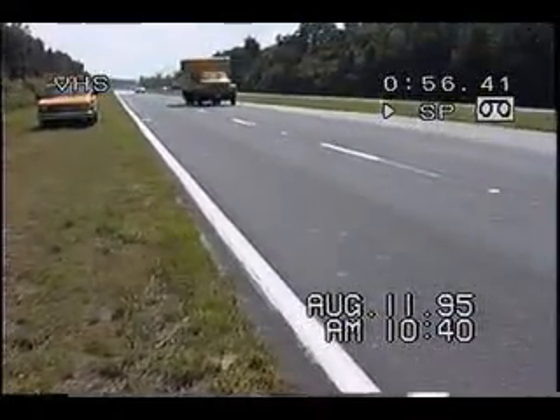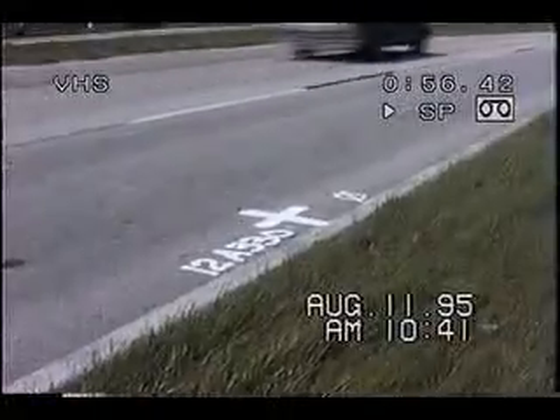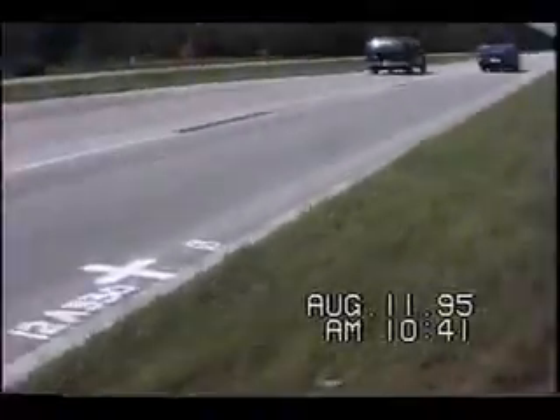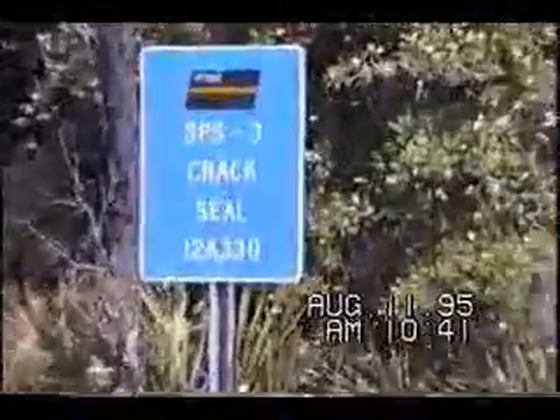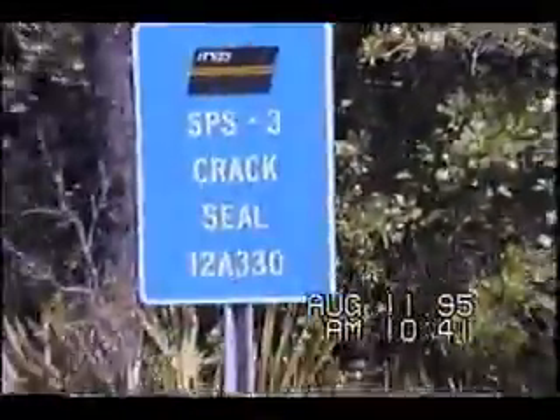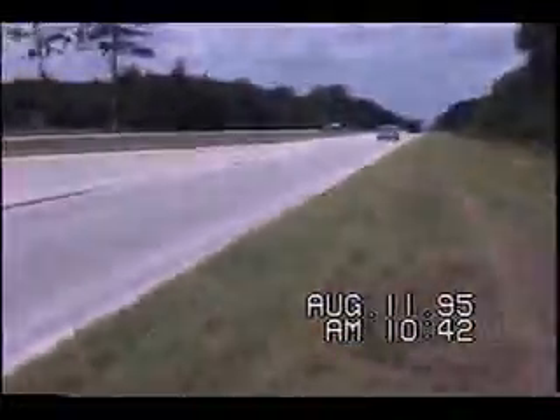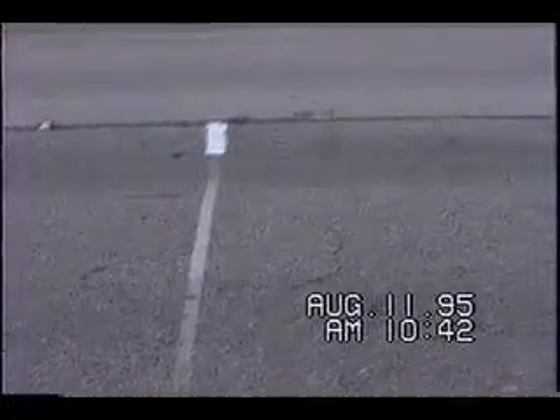They came through here to do the sealing, they didn't have to do much sealing. There wasn't much in the way of cracks. We did, however, find quite a bit of cracking, a lot of fatigue cracking for that matter, as well as transverse cracks. We found quite a bit of cracking out here on the very inside edge of the test section.